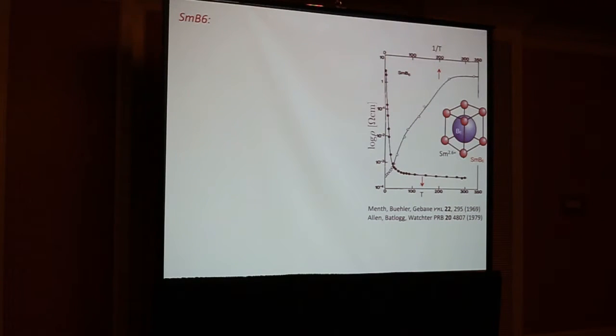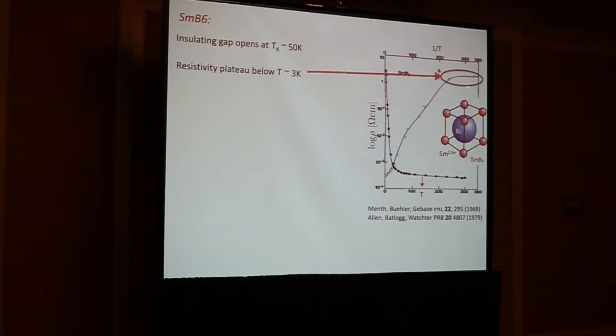But if you replace lanthanum by samarium, which introduces a local f moment, you transform the properties from a metal at high temperatures into an insulator with a narrow gap at low temperatures. It has an insulating gap that opens up at 50 Kelvin. It's kind of mixed valent. And it develops an unusual resistivity plateau below about 3 Kelvin.